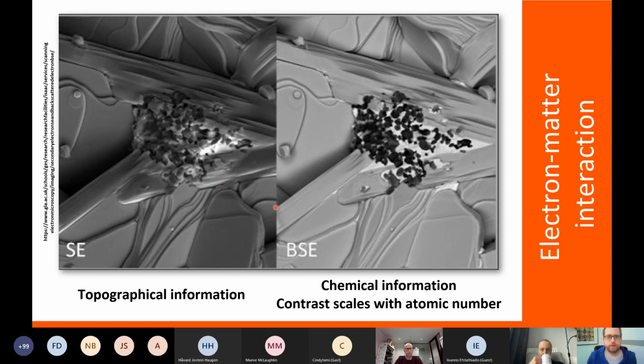So here are two images of the same material, of the same area, but one is collecting secondary electrons on the left-hand side and backscattered electrons on the right-hand side. And you see the immediate difference. We have a material with some particles on top of it. In the secondary electron mode, we see topography. We see actually that these particles here are topographically higher on a material that actually has quite a bit of topography itself.